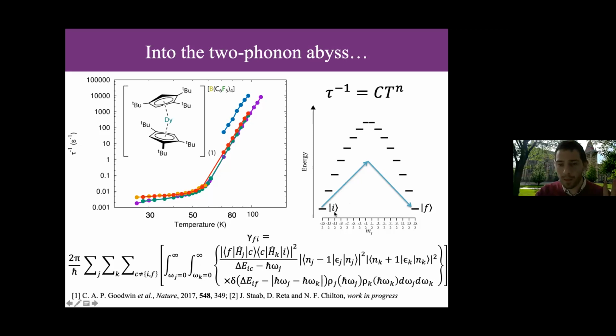But anyway, the point is you sum over all intermediate states C. So anything that's not I and F, you are trying to see how the vibrational modes mix states I, the initial one, and the final one, F, via a state C through spin-phonon coupling. So this is second-order time-dependent perturbation theory using first-order spin-phonon coupling. The first-order spin-phonon coupling is these matrix elements here, so that hasn't changed from before, but we are now doing the second order in time-dependent perturbation theory. And so we never transit via a real state, and the contribution is via all excited states C. So I like drawing it like this, and this is the meaning of a virtual state. It's never populated in this transition. It's just perturbation theory.